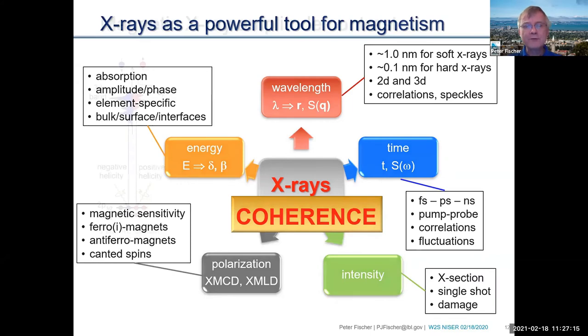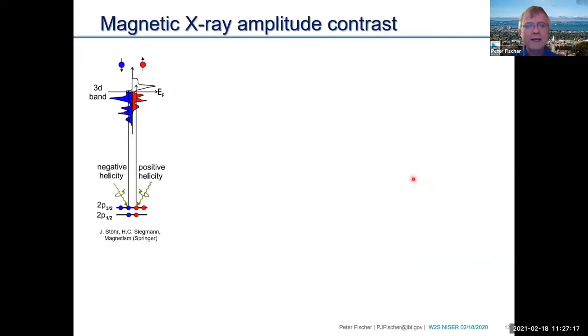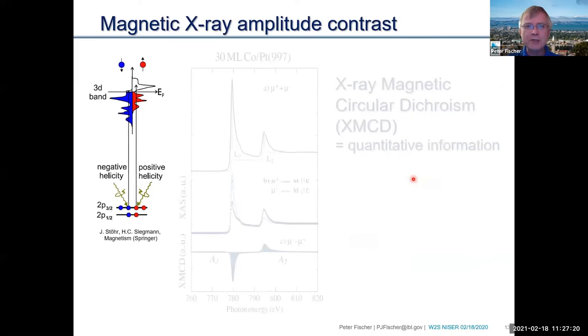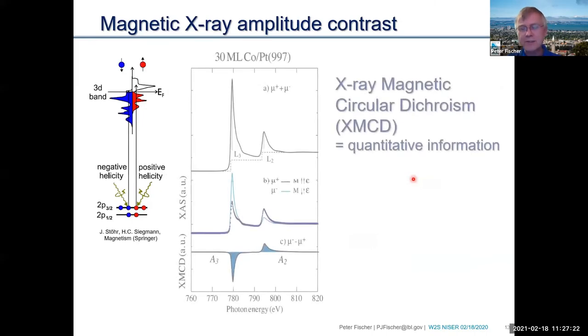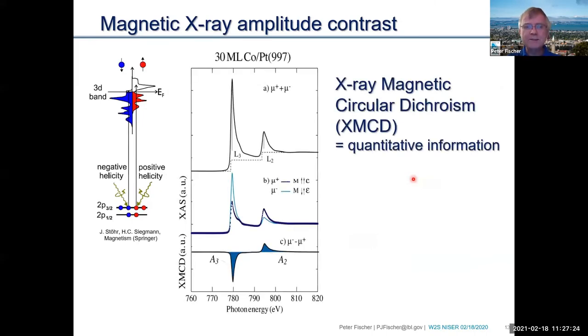Okay, very briefly, probably most of you have seen this already, the contrast mechanism that we need for imaging is based on X-ray magnetic circular dichroism. I mentioned it before. This is the counterpart of the magneto-optical Kerr effect, but now we're in the X-ray regime. And to make it very short, when the X-rays come in with a certain energy and match the binding energy of an inner core electron, this electron gets excited, ejected, or transferred into a state at the Fermi level.